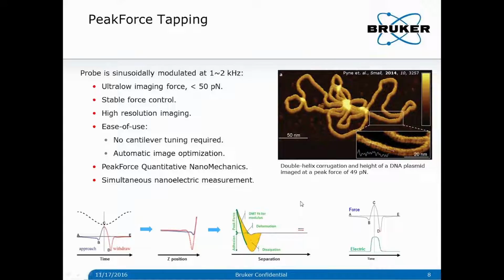Another feature of peak force tapping, because it's doing low-frequency tapping, is that during each tapping cycle it has a contact duration. For example, here from the snap contact to the break contact, from B to D, it has a duration of about 100 microseconds. So this is a magic. This is really a nice duration because it doesn't require very fast electronics. For example, if you have a sensor circuit that has 10 to 20 kilohertz bandwidth, then you can effectively capture any electrical signal during the tip-sample contact in this duration. So it also provides a simultaneous nanoelectric measurement.